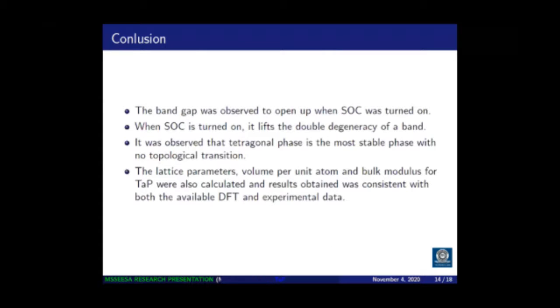So as I conclude, I was able to observe the energy gap when I applied the spin-orbit coupling. Then I've also been able to note that actually the tetragonal phase is the most stable phase. And in this particular phase, there is no topological transition. And the other parameters were very much in agreement with the other studies.